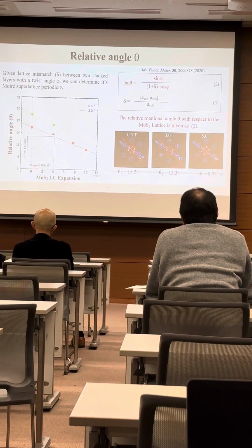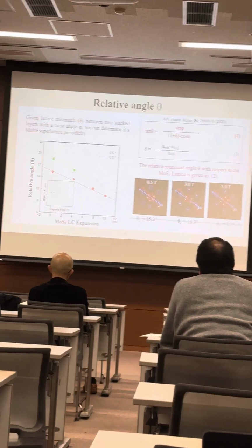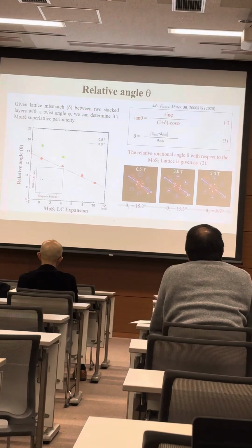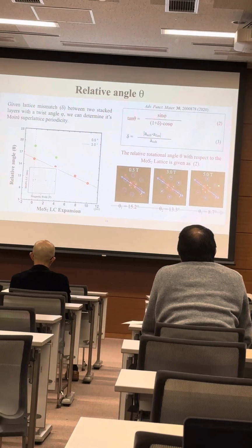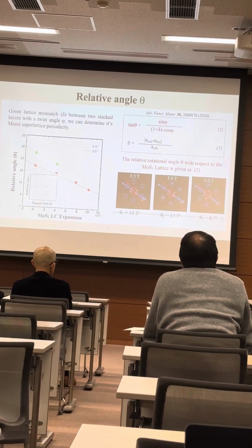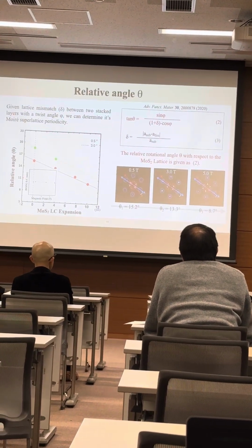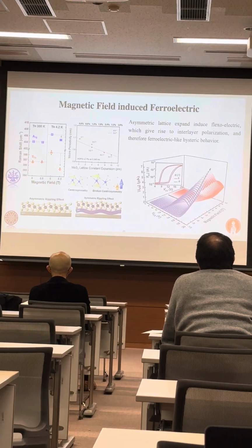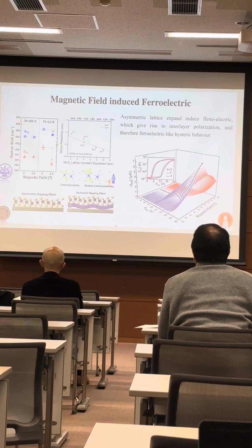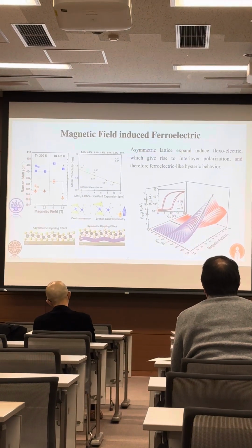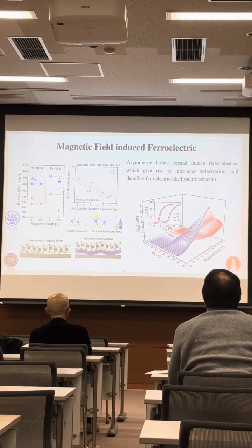So one thing worth noting is that under different magnetic fields applied, the HOPG substrate will remain the same lattice constant. So that's why we could deduce the variation solely came from the MoS2 lattice, since the delta function here is only changing by the lattice constant of MoS2. So with our findings above, we could confirm that in real space, MoS2 lattice will experience tensile strain that will give rise to lattice expansion, instead of the phase transition to 1T phase that we thought about.